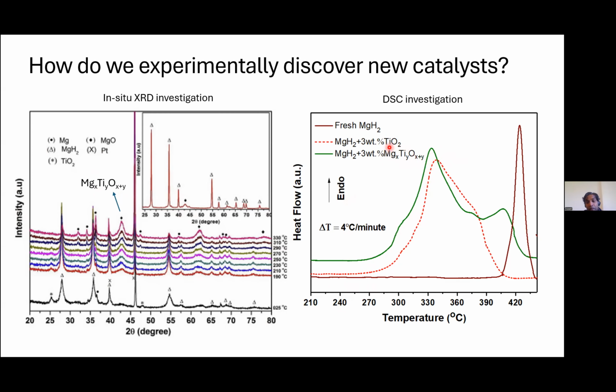But the story is that there can be several active species, and when you change the transition metal and repeat these measurements, you can find out what can be the universally best active species among whatever materials are available in the periodic table. If you identify that, you will solve this issue for the betterment of humanity forever. That's the importance of these kinds of works.